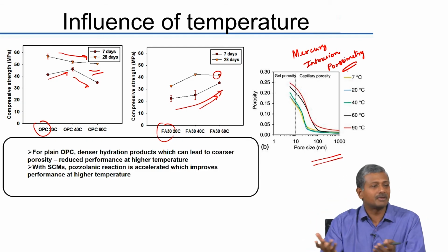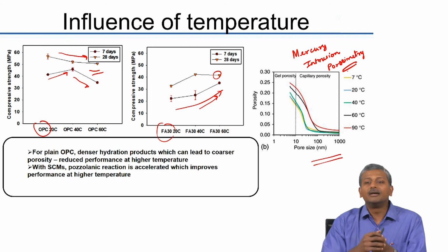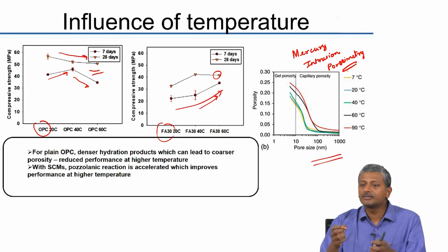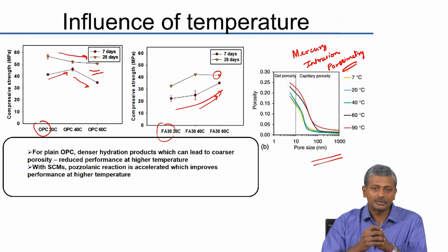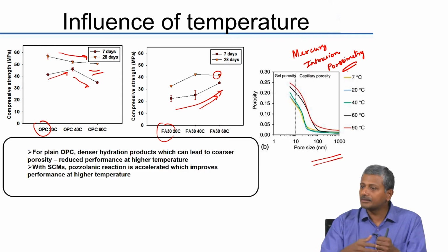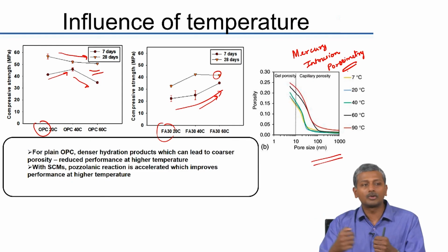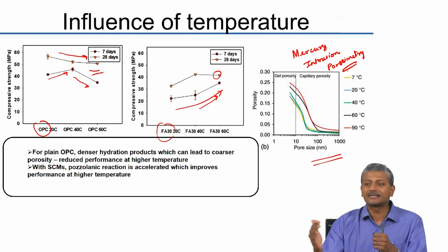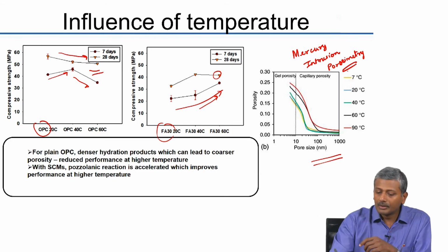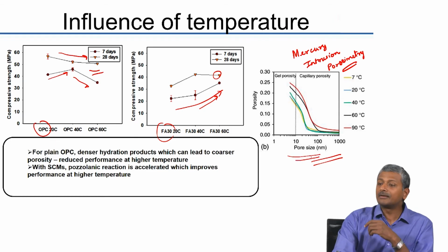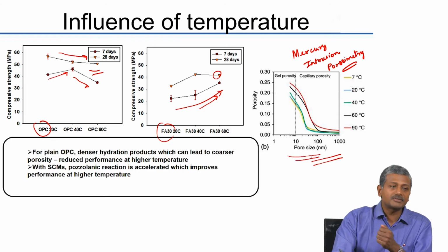And you know very well again from the capillary equation that at higher pressures you will penetrate the smaller and smaller diameters of the pores. So all we do is simply make the mercury penetrate into the pores under an increasing set of pressures. So the pore size distribution can as a result be obtained from this experiment.